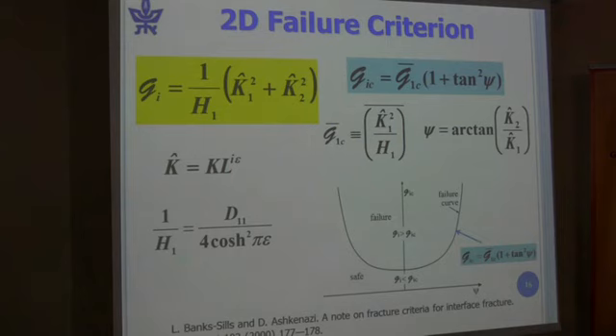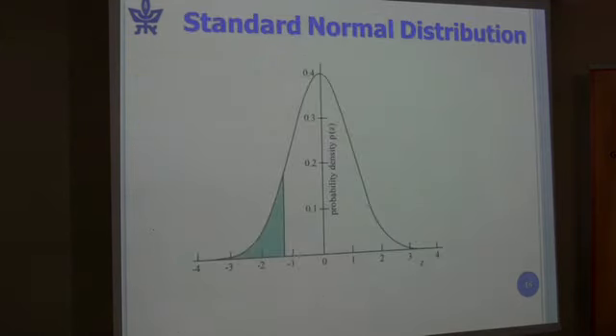What is the problem with this? The problem with this is statistically, we have points below the curve which fractured in our tests. We have test points below the curve where it should be safe. And that drove us to do a statistical analysis. So to say that I'll give you a new curve, which will be more conservative, it'll be lower, but then I'll only have a certain percentage of probability of failure in that safe zone. So that's what we did.